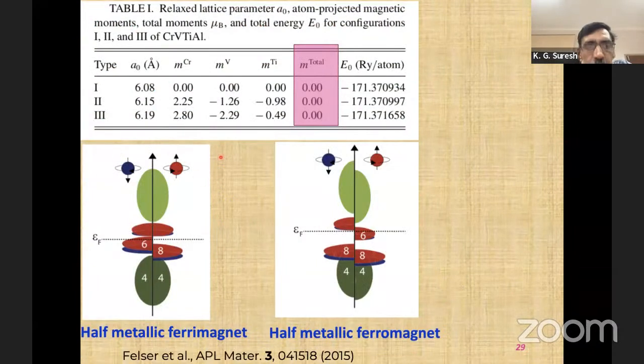Then when we did the calculation, we found that every individual constituent has some magnetic moment. There are actually 3 crystal configurations, non-degenerate configurations, for this particular crystal structure. And then we found that the configurations are like this. They are not energetically very different. The energy separation is not very large, at least compared to room temperature. And in all these cases, you see that the total magnetic moment is close to 0. This is a theoretical value, and more or less what we obtained from the experiment also. So this basically led us to conclude that this is not an antiferromagnet.